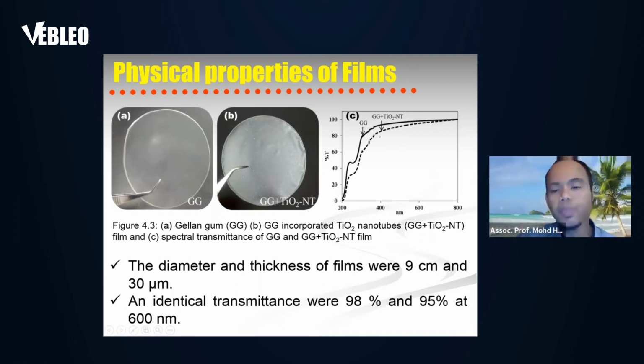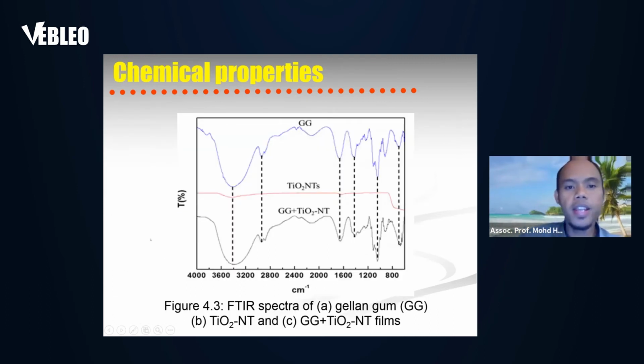Okay, as expected, when we include the titanium dioxide nanotubes in the film, the transmission rate was reduced to 95% due to the presence of titanium dioxide nanotubes. Okay, and then the diameter and thickness of both films are almost similar, 9 cm in diameter and 30 micrometers in thickness. Okay, and then we come up with FTIR spectra in order to study the chemical properties of both films, and we can observe that the FTIR spectra for both films are almost similar.